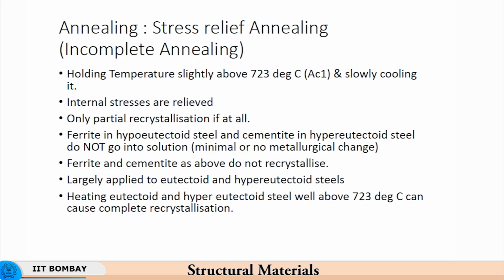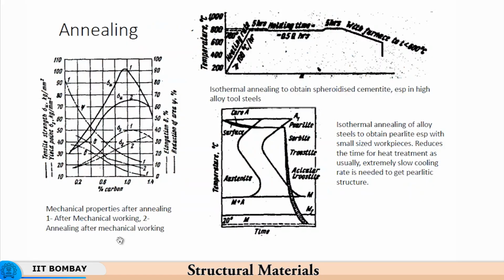So, there is local yielding taking place and the stresses get relieved, but the microstructure as such does not change, in the sense that no new crystals would form, and the dislocation density is also not changed.